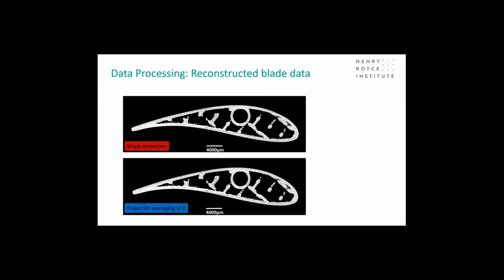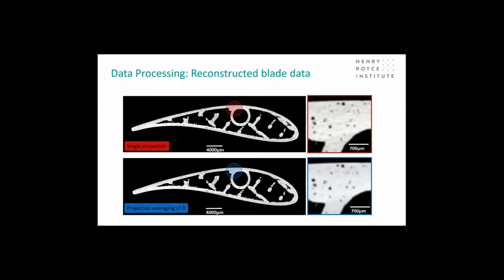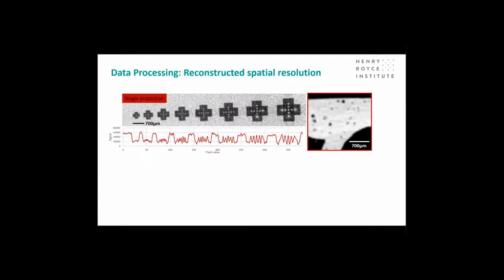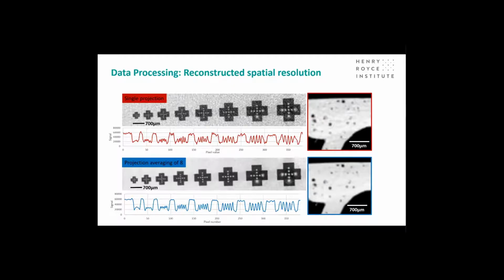And in order to do that, one has to be careful to make sure that the quality of the images are sufficient. Here you can see a single projection on the top, and at the bottom you can see a projection averaged over 8 different frames, and you can see that the noise in the top signal is significant compared to the bottom. And you can qualify that using calibration samples. Here's a simple calibration sample, and you can see that if you compare the top single projection image of those calibration samples with the bottom one, which is averaged over 8 images, you get a much better definition of those pores.